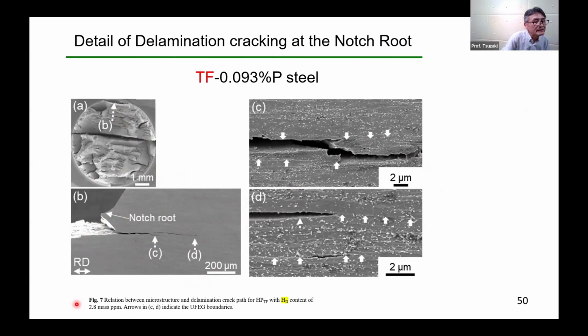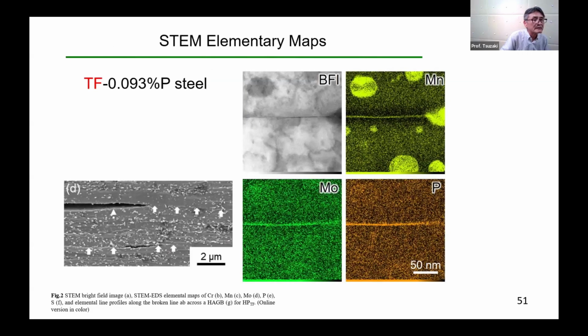Delamination has occurred near the notch root, like this. And as you can see in the magnified images in C and D, the delamination propagates along the grain boundary. Therefore, we are concerned about the elemental segregation at the grain boundary. Next, I show you the STEM elemental maps.